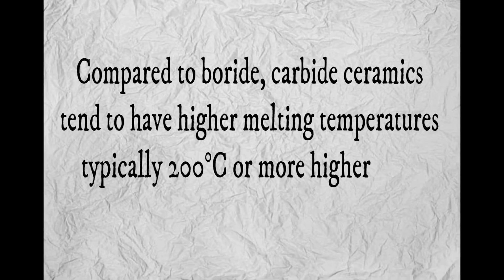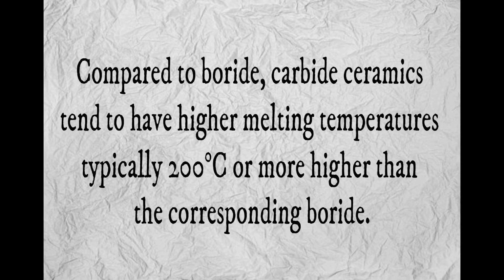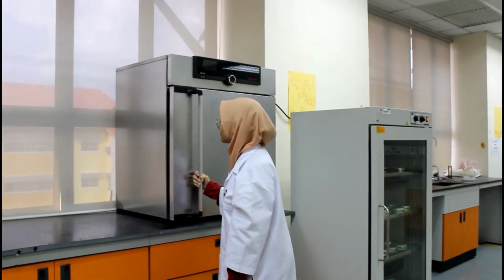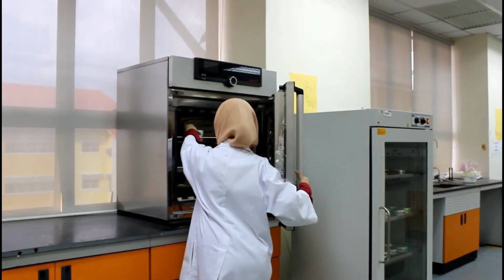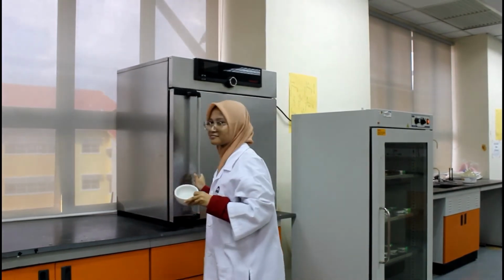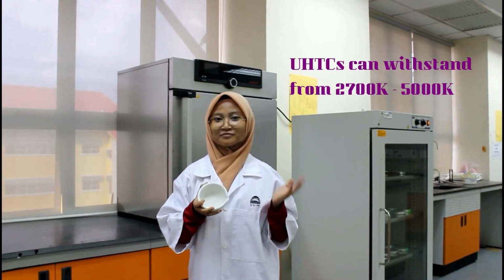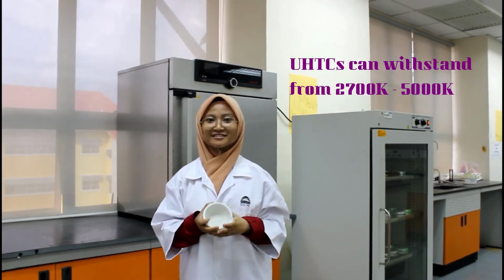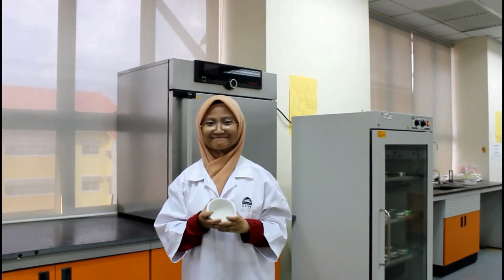Compared to borides, carbide ceramics tend to have higher melting temperatures, typically 200 degrees Celsius or more higher than the corresponding boride. This ultra-high temperature ceramic can withstand from 2700 Kelvin until 5000 Kelvin.